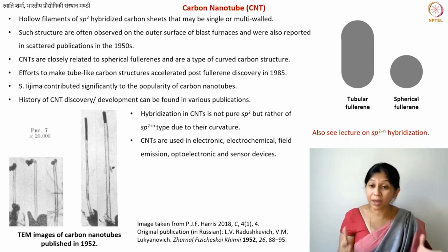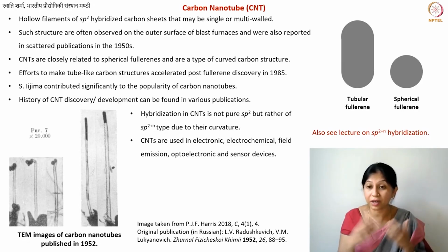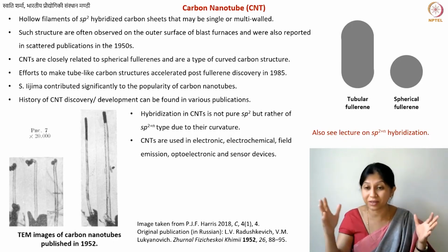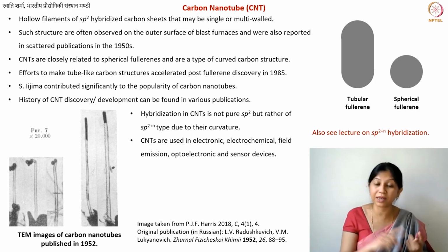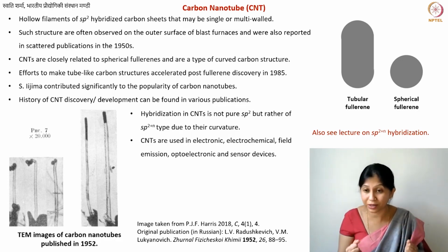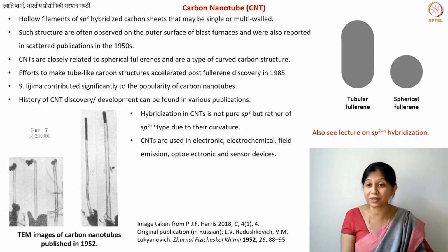Okay, but some of it has been experimentally validated, some not, because you can imagine that you have these extremely thin structures. Single walled carbon nanotubes can be 1.72 nanometer in diameter. The aspect ratios are typically high for carbon nanotubes. There have even been reports of several centimeters long carbon nanotubes. But the point is that it's also a very sensitive thing. If you have single-walled nanotubes or multi-walled nanotubes, already the properties differ a lot. Also, the electrical properties differ a lot.